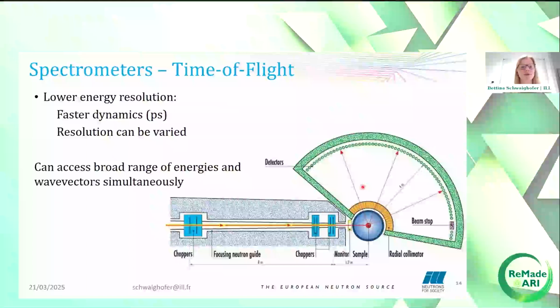So first, starting with time-of-flight spectrometers. Generally, time-of-flight spectrometers give access to a lower energy resolution than the other spectrometers, and therefore we can access faster dynamics, like on picosecond timescales. The resolution can be varied, which makes time-of-flight spectrometers very versatile instruments. And we can access a broad range of energies and wave vectors and obtain maps of the S(Q, omega) space.